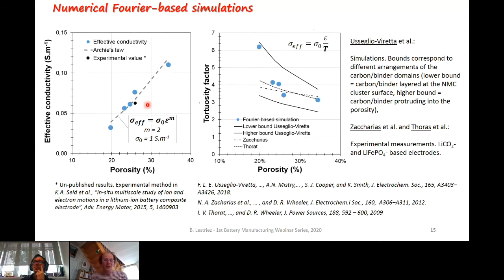Others are coming, but it's not easy to discriminate between the ionic conductivity and the electronic conductivity in a composite electrode that is containing the electrolyte and the CB-PVDF domain. So at the moment, we have only one experimental result, but it is in fair agreement with the simulations. And on the right, we have calculated the corresponding tortuosity factors through this equation. So the classical equation, the results are plotted in blue, and they are compared to trend results from the literature.